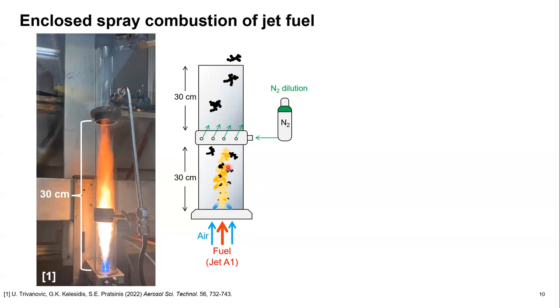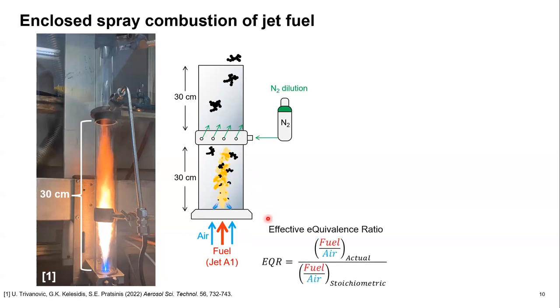All of this is enclosed in two 30-centimeter long quartz glass tubes, which allows us to control the exact amount of air and fuel in the system and prevents air from being entrained from the outside. So we control the particle properties by varying the effective equivalence ratio, or the EQR. The EQR is the actual fuel to air ratio divided by the stoichiometric fuel to air ratio. So an EQR of 1 is a stoichiometric flame, and